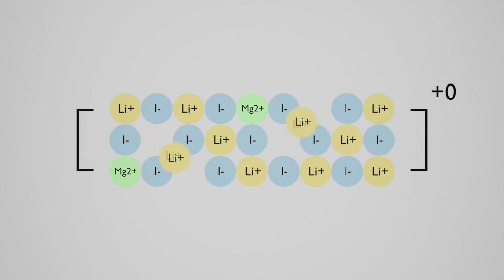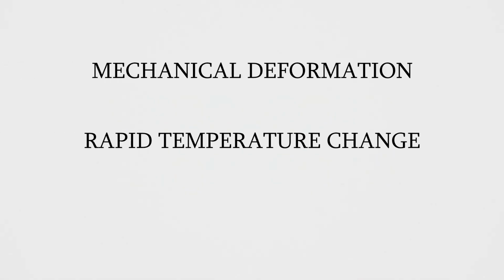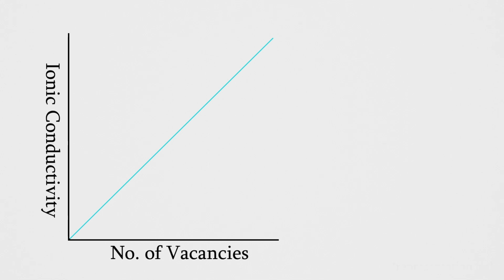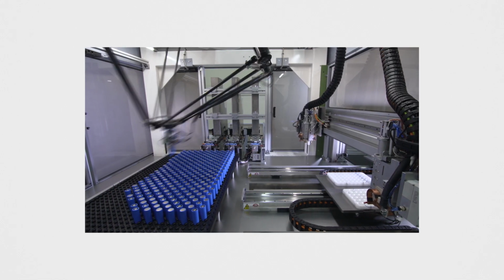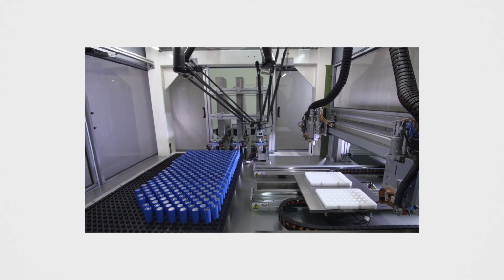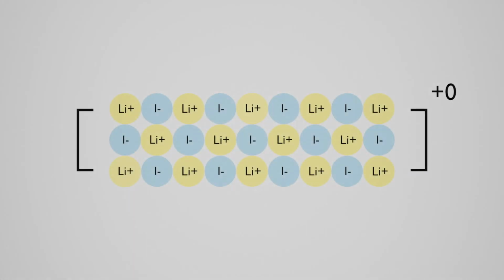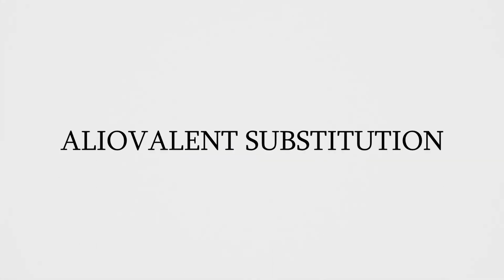What is particularly promising is that these vacancies can be forced by mechanical deformation, rapid temperature change, or even exposure to radiation. Furthermore, ionic conductivity is scaled with the number of vacancies. This would theoretically allow for the large-scale production of efficient solid-state electrolytes. However, creating vacancies causes a charge imbalance in the crystal that would destroy it if not treated. This charge imbalance is treated by aliovalent substitution.